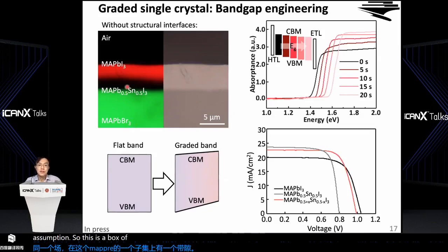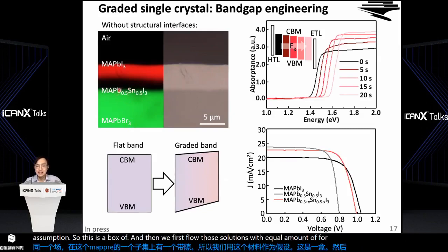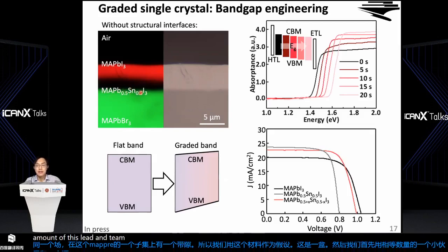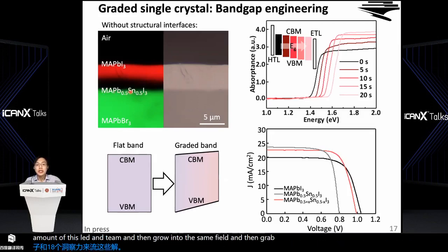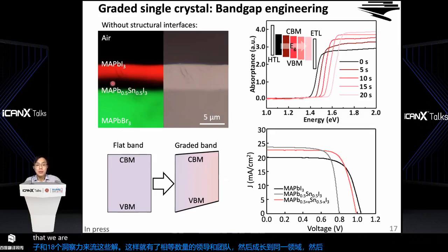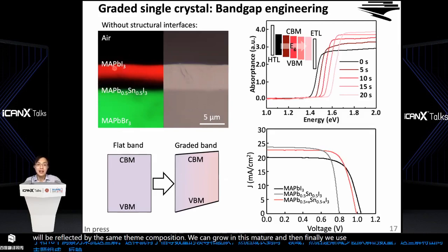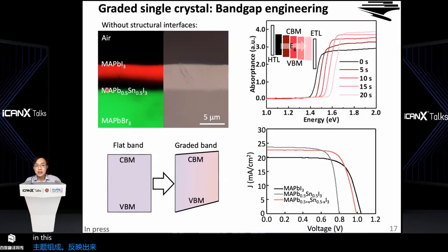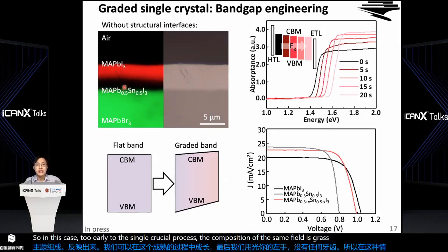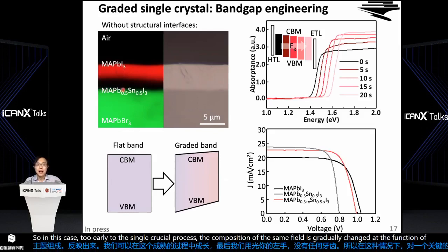And then we first flow those solutions with equal amounts of lead and tin inside. So we have this equal amount of lead and tin, and then grow into the thin film. And then gradually we reduce the amount of the tin solution. That will be reflected by the thin film composition we can grow in this material, right? And then finally, we use pure lead without any tin. So in this case, during the single crystal process, the composition of this thin film is gradually changed as a function of thickness from the bottom to the top, right?